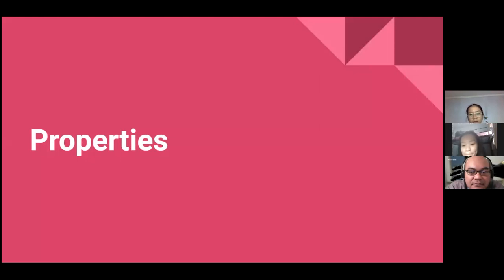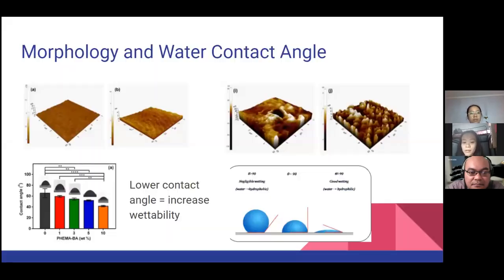So after fabricating the contact lens, the researchers are assessing the properties of the material that they made. So first is the morphology and water contact angle. As we have known earlier, after Anjali's presentation, the boric acid is the independent variable, so it is the one that they change. And here are the parameters. Here, this is the morphology when using only 1% of boric acid, and this is the morphology of the hydrogel when using 10% of the boric acid. As we can see, it has a rougher surface in the 10% boric acid. So it means that an increase in boric acid means that the morphology is rougher.